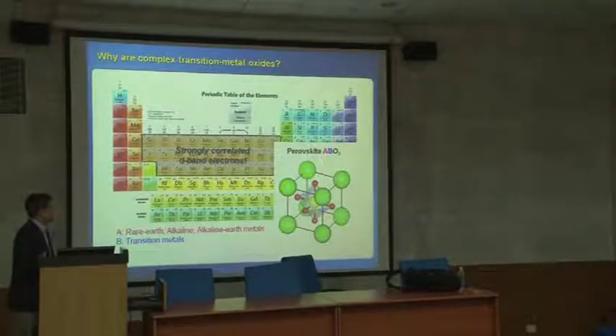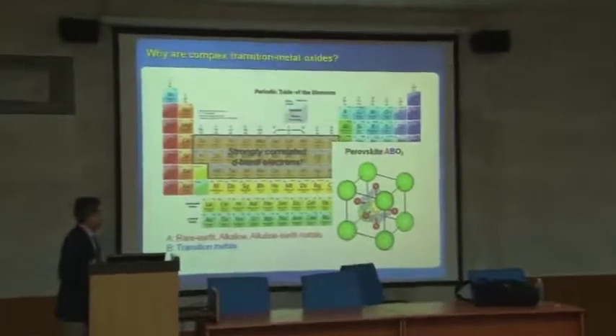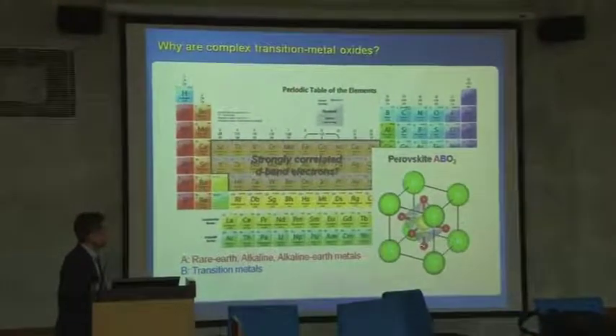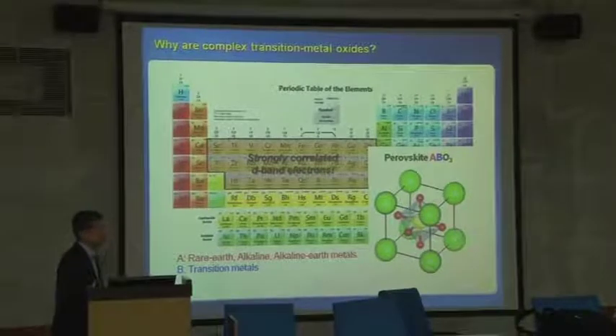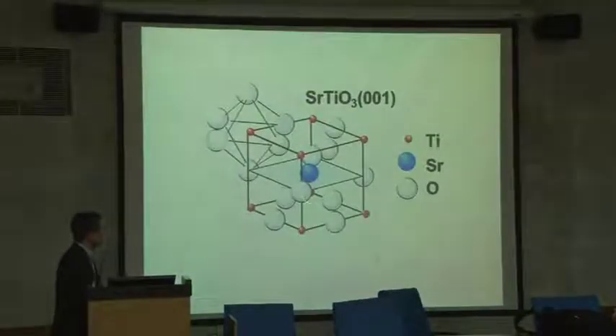So the perovskite structure is an ABO3 structure, as I said, and this octahedra and A and B site cation plays a very important role. Let me just talk about a simple and the most well studied material system, strontium titanate, where strontium goes to A site and titanium to B site. But I just made a different reverse structure, and I put Ti in A site here and B site here.